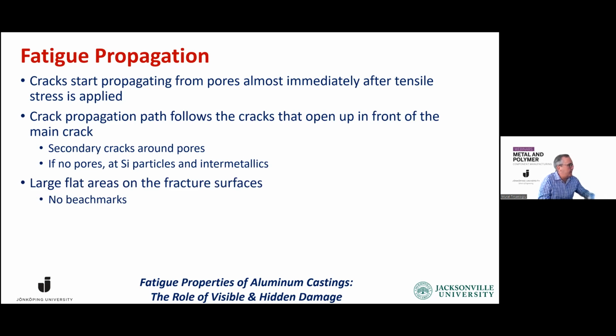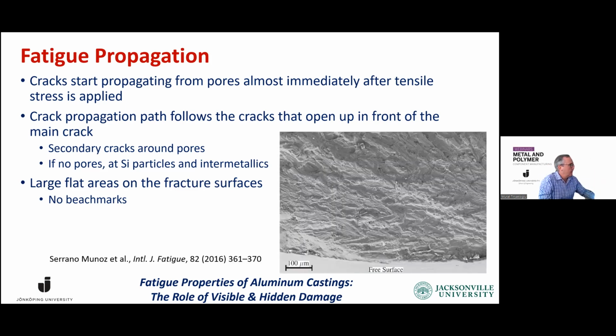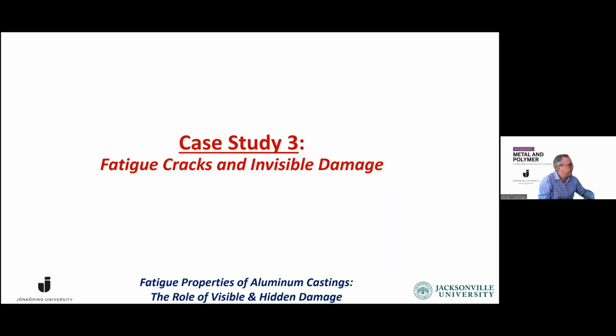And in high cycle fatigue at room temperature, there are large flat areas on the fracture surfaces where we don't see any beach marks. All we've learned when we were taking the first lesson in fatigue, how we see beach marks on the propagating crack, and all of a sudden we don't see those. And here's an example, large areas that are completely free from beach marks. Cleavage, a lot of cleavage going on. Okay, this brings us to the next case study.